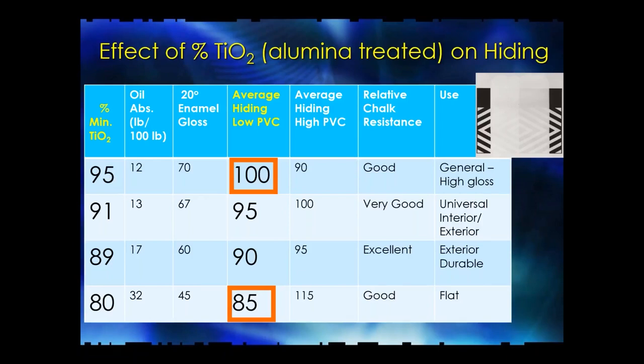And that actually rides on the surface. 50% of the soluble alumina rides on the surface of the raw titanium dioxide. So there's really no such thing as titanium dioxide that's 100% pure. And then on top of that, they'll add 3 to 4% of alumina, and that alumina is precipitated down on the surface from water, and you find that that has the magic boehmite, and it has the magic amorphous alumina.